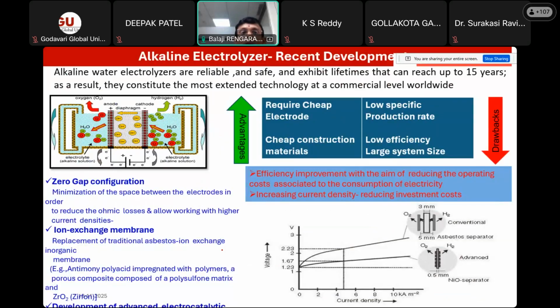Coming to the alkaline aspects, there are 3 different types of water electrolyzer: alkaline, acidic, that is PEM, and solid oxide. In the case of alkaline, the advantage is that you can use a non-noble metal-based electrocatalyst. You can use nickel, cobalt, or iron. This kind of cheaper material can be used as an electrocatalyst for alkaline water electrolysis, and because of that, the overall capex of the system will be low. But in the case of disadvantage, because this is an electrochemical cell, how can you make a very efficient electrochemical cell?